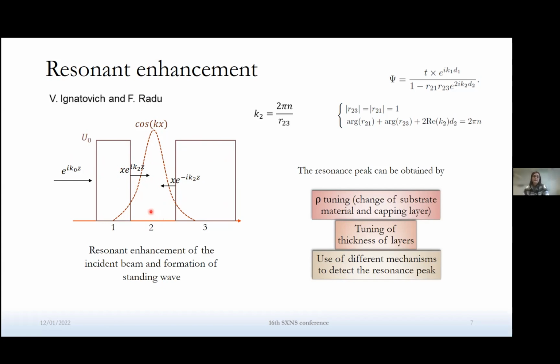So in order to get this resonant enhancement, the only requirement is that our scattering length density depth profile has a shape of a well, and that means that we must sandwich our layer of interest between a substrate and possibly a capping layer with a big contrast in scattering length density. Moreover, we also must have a channel which is proportional to the neutron density that allows us to detect this resonance, and this can be spin flip scattering, secondary particles such as gamma and alpha, incoherent scattering, or even transmission.